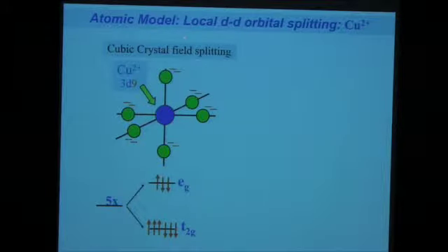How does the local copper 2+ environment look like? So the most simple-minded picture to understand that you can get from chemistry, where you look at the cubic crystal field splitting of a copper 2+ ion, which has 9 d electrons, so one hole, as I mentioned before, sitting in a cubic surrounding of negatively charged oxygens. These negatively charged oxygens split up the local 3d states. So in principle, 10 electrons, I have 5 times 2 states for the d electrons, and this 5-fold degeneracy for the ion is split into a set called t2g orbitals, and the other ones are called eg orbitals. I'm sorry for these names, that's historically what they are called.